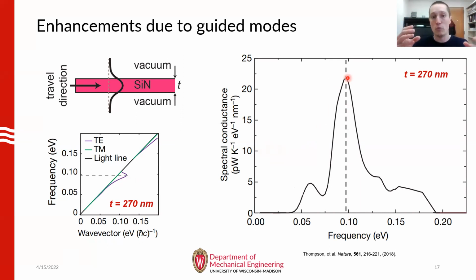So it turns out that regardless of the thickness of these nanomembranes, they will always support one branch of the TE and one branch of the TM modes, regardless of the thickness. And this is completely not accounted for by Planck's theory, which assumes that the electromagnetic modes in a structure are completely confined by its geometrical dimension. So that would essentially underestimate the photon density of states that are present in our nanomembranes.